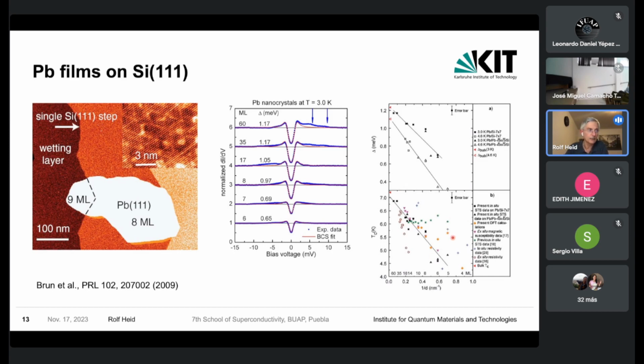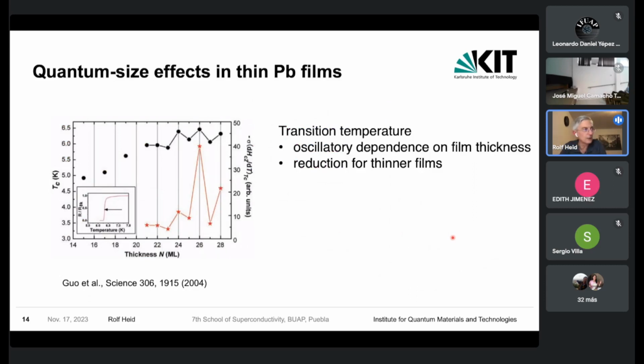Now, this trend has been observed, although you can see here that the scattering of the data is quite large, but there has been another nice observation. When you look at the transition temperature at some thinner films, with monolayer thickness in the case of between 14 and 28, you see that the transition temperature has a kind of oscillatory behavior before it finally starts decaying. The question was where this oscillatory behavior is coming from, and one origin was pointed out early on: that this might be due to the quantum size effect in these very thin films.